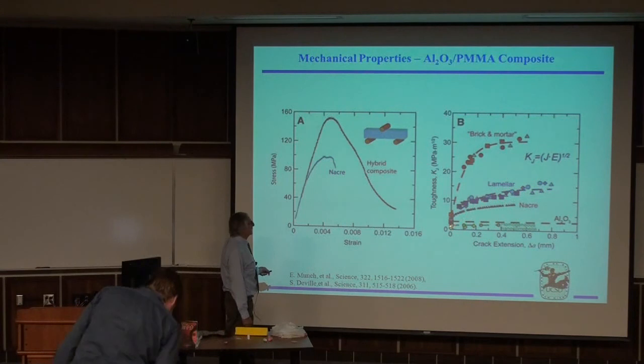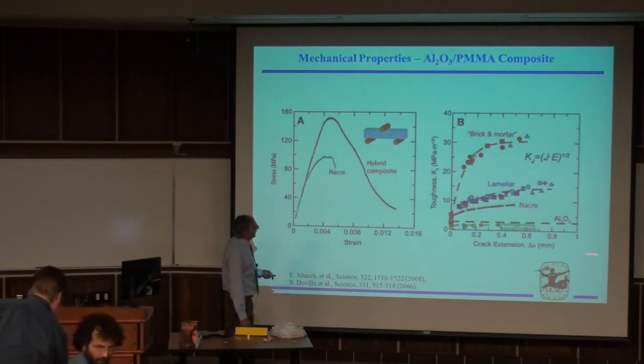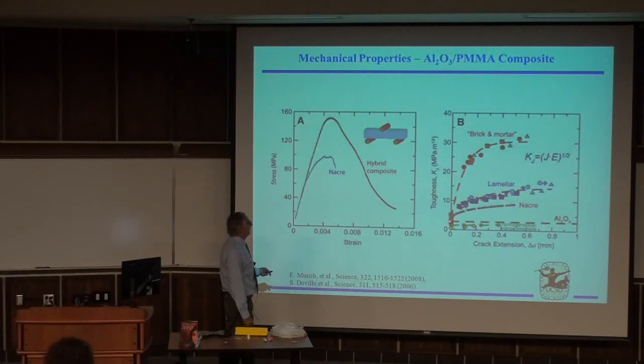Nacre goes like this. Nacre starts slow, but you see that it increases as the crack increases. That's the R-curve behavior, and that's the desirable thing. There are extrinsic and intrinsic toughening mechanisms operating in nacre. So nacre is tougher than alumina. And the highest one is the brick and mortar alumina PMMA composite made by Ritchie and Tomsia. It went up to 30 megapascals root meter. That's fantastic. No other ceramic, with 95% alumina, no other alumina composite can reach this. So this is, I think, one of the top.